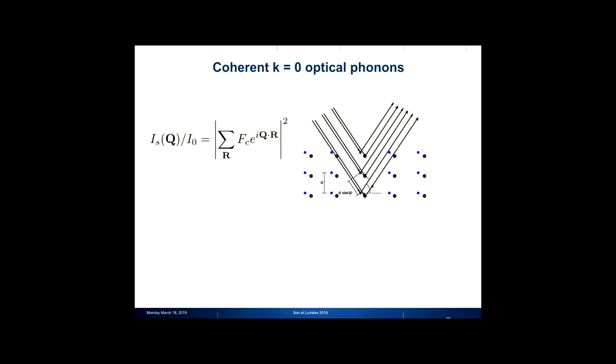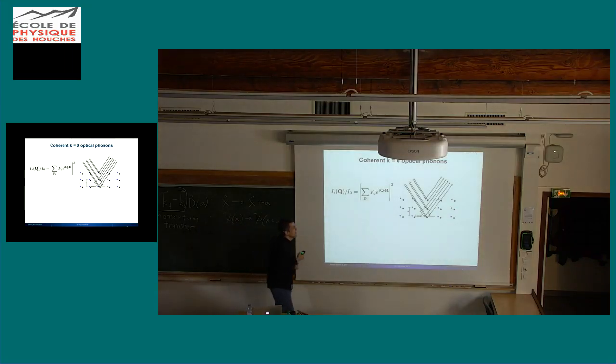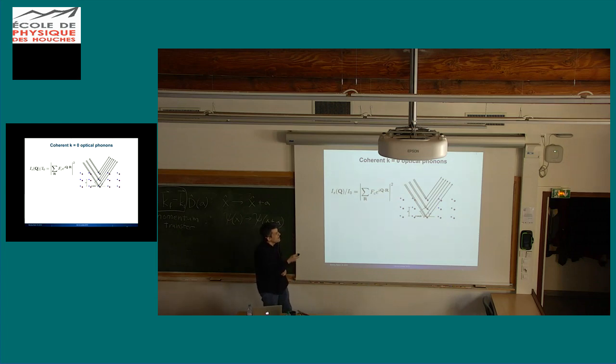All right, so I wanted to show some examples of things that actually happen with reference to coherent phonons. K = 0 optical phonons are probably the easiest to explain, at least for me. This is a very simple lattice consisting of a basis set of two different atoms. The idea behind K = 0 optical phonons is that these are relative motions of these two atoms with respect to each other that are identical in every unit cell. In terms of X-ray diffraction, you can think of this as interference between two sublattices, and that interference will result in variations of the intensity at particular Bragg peaks.